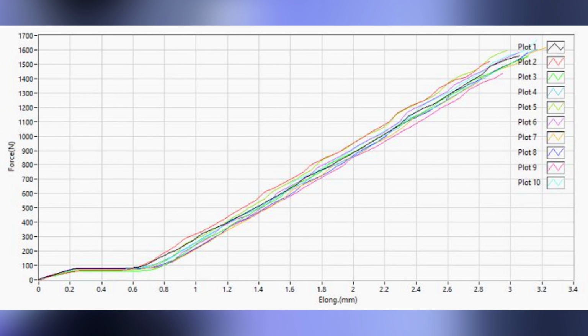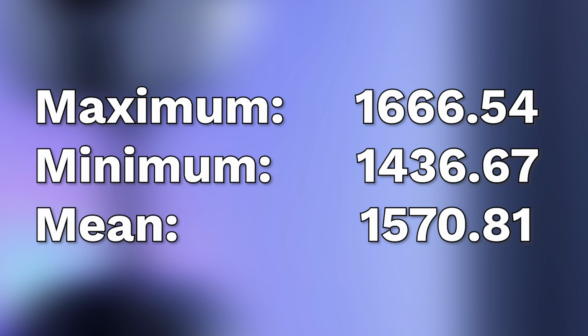Pop that a few times, and then we end up with an average force that it was able to withstand of 1,570 newtons, which is only slightly lower than the standard PLA, which is great news because when you have a manufacturer tell you we made PLA, you expect it to be the PLA. Ingeo 4043 was effectively the original PLA. There was another variant from Corbion, which was kind of, not a knockoff, but a similar formulation and similar properties. Ingeo 4043 is very certainly what most manufacturers mean when they say PLA.